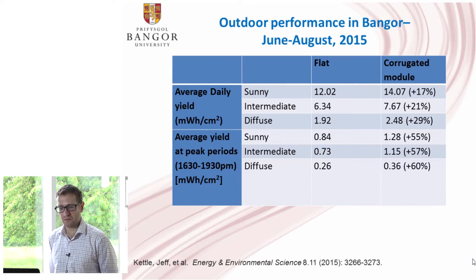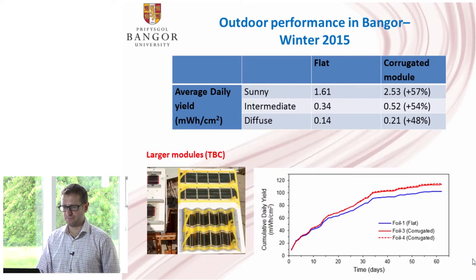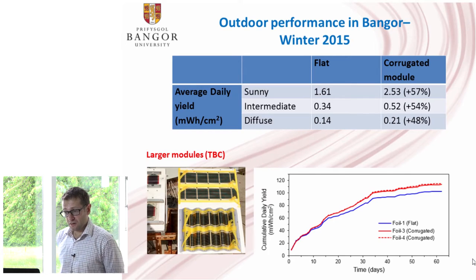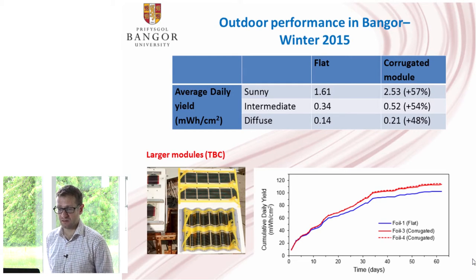And the other significant point to add is that if we consider peak electricity periods, which tend to be 4:30 p.m. to 7:30 p.m. in the UK, we get an even bigger relative increase. So our corrugated module gives around about 60% increase in energy yield during those peak operating times. So we started to look at the performance over winter as well, and our winter data even improves over our summer data. So we get these bigger and bigger relative increases in performance from the corrugated module over the flat module.